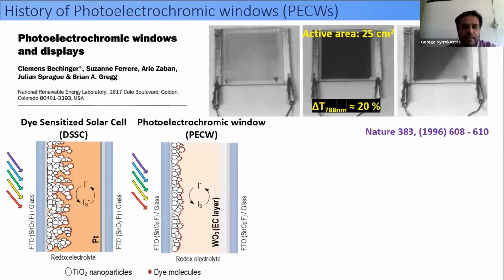The architecture of such a device was very similar to that of a dye-sensitized solar cell. In the case of a dye-sensitized solar cell, at the anode we have a nanostructured titanium dioxide film with thickness above 10 microns, sensitized with an appropriate dye. At the cathode we have a very thin platinum film, and between them there is a redox electrolyte like an iodide/triiodide one. And the role here of the cathode is to collect electrons from the external circuit and to catalyze the reduction of triiodide ions to iodide.